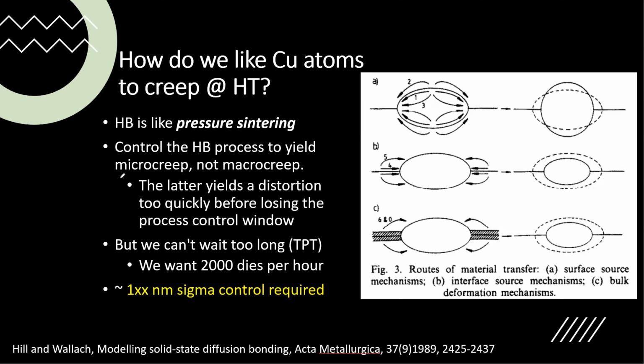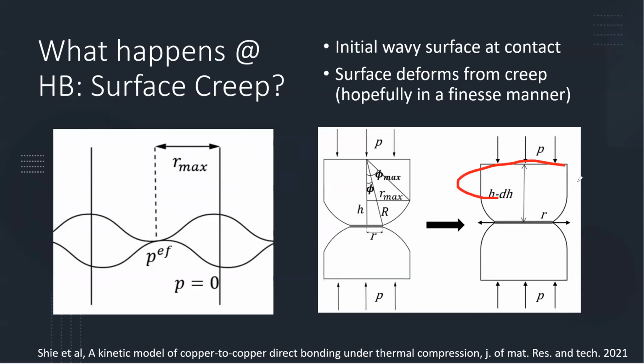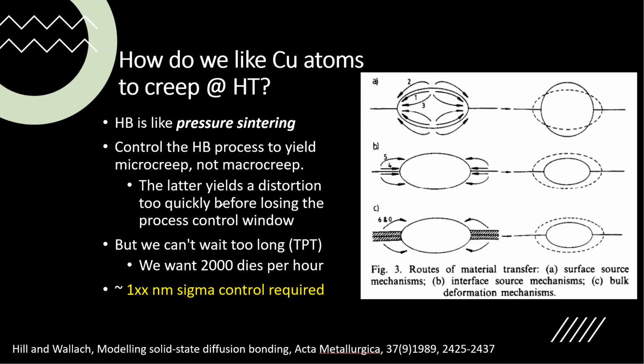All right, so all these three sources you have to control in a process way, so that at the end of the day you want to have a micro creep, not a macro creep, because macro creep means that it deforms too much. The whole thing deforms too quickly. You want a local, microscopic deformation that you can control. If you use too much force, then you go to macro creep, and that creates distortion too quickly. Then you lose the process control window.